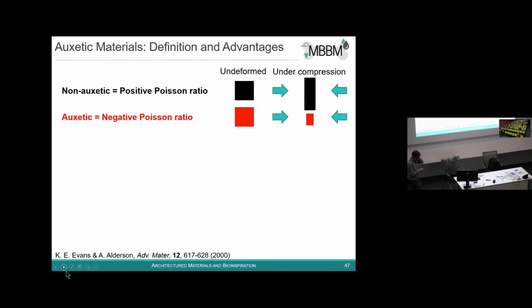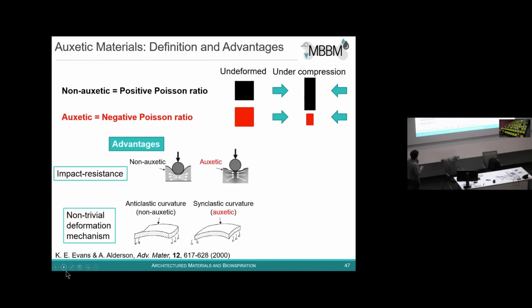Well, there are several applications that one could think about for those materials. One application is that it is known that they show enhanced impact resistance, because in a non-auxetic material, when you have a local indentation, the material has the tendency to flow away from the indentation point. And in an auxetic material, the material has the tendency to concentrate at the indentation point. And so this is then sustaining the impact more.